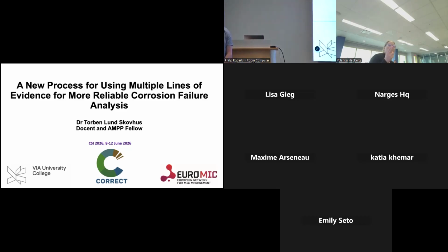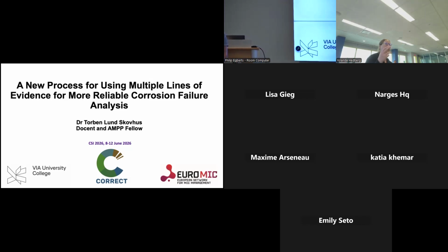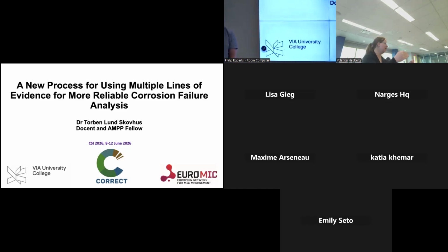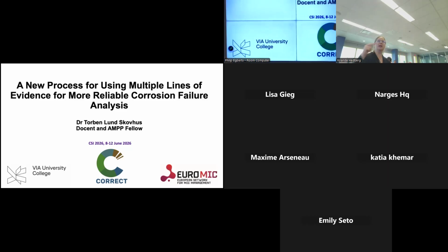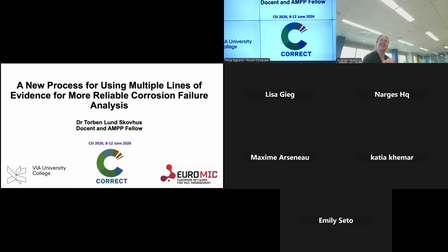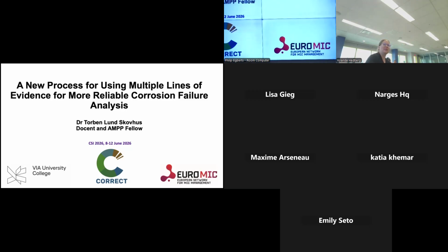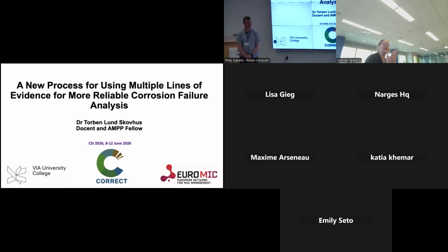And there is one of my mentors, Paul Linhardt in Austria. He does a lot of MIC failure analysis. So he goes to the plants, the hydroelectric plants. And there he put an electric sensor on one of the corroding turbines. And the funny thing was that the potential was changing over day and night time. And he figured out that those algae were actually involved. So there are really cool things you can do in this area because every case is new, right?